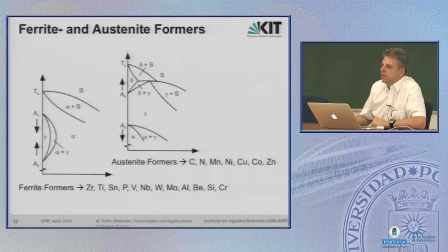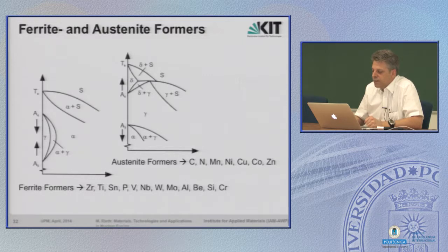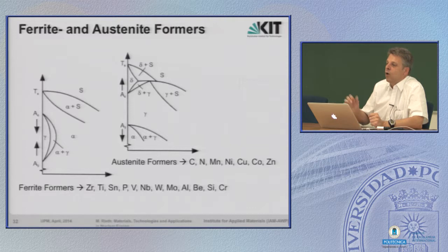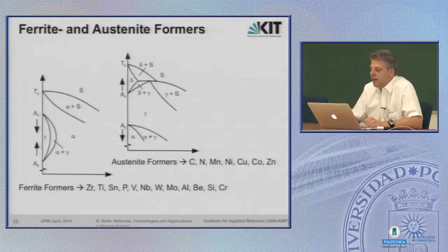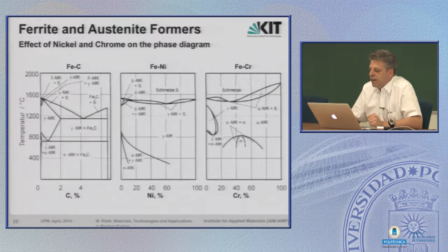a Eurofer type steel. Then the other example, austenitic steel: you have to add, let's say, a lot of manganese, also some nitrogen and nickel, for example. This enlarges very broadly the gamma field, the austenite phase. And in the end, if you have enough of this element inside, you have only one phase field, that's gamma. You can heat up or cool down the steel, it doesn't matter. You always end up in an austenitic phase, in an austenitic steel. So this would be the case for the 316 stainless steel.